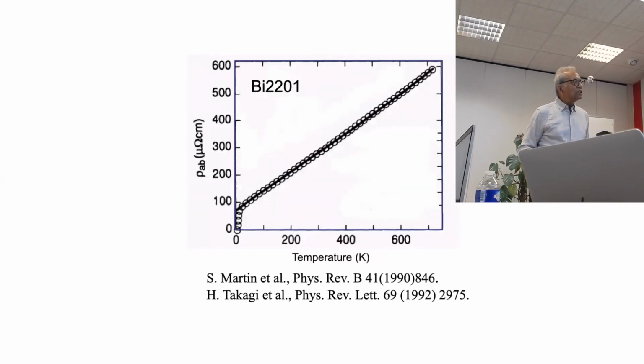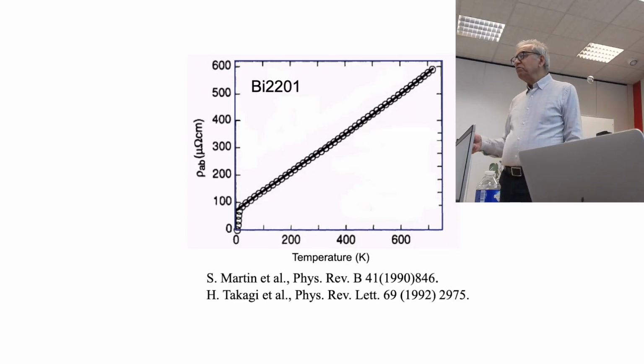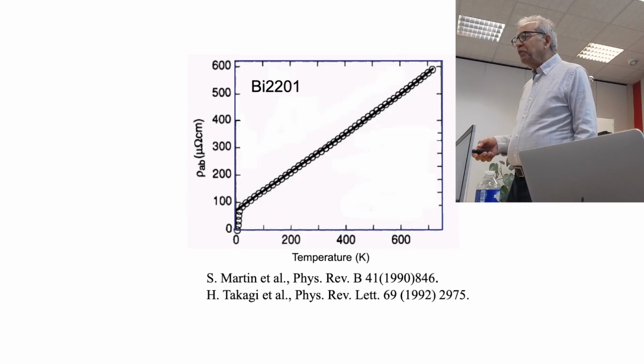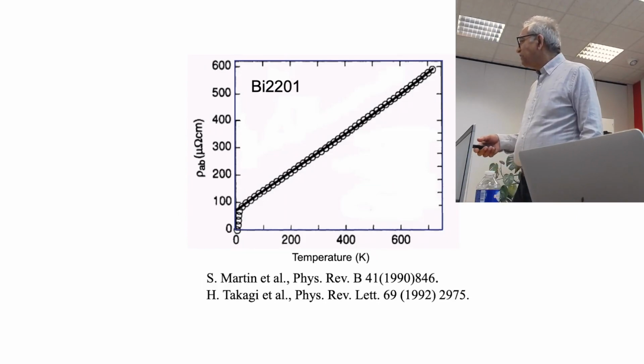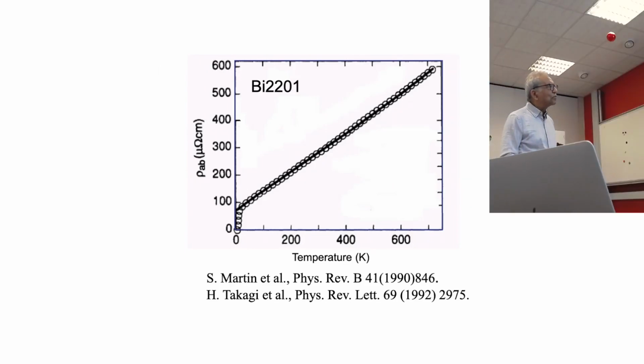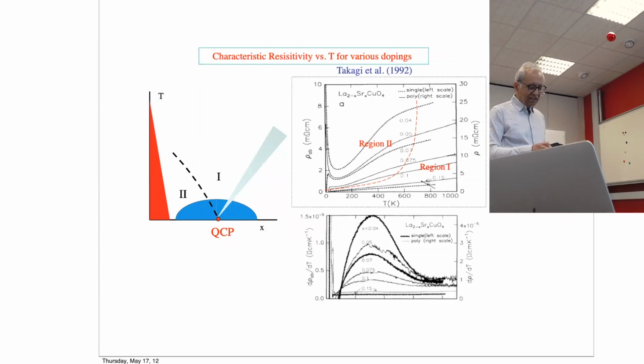So here's an early measurement, already in 1990, of a compound whose TC was 7 Kelvin. And the resistivity, this is experimental data on that one. And now we have doped lanthanum cuprate, where you can reduce TC to about 2 Kelvin, and you can see that this thing persists. This thing changes when you go to this part of the phase diagram. For example, here is data in lanthanum strontium cuprate, and in this region you have this linearity.